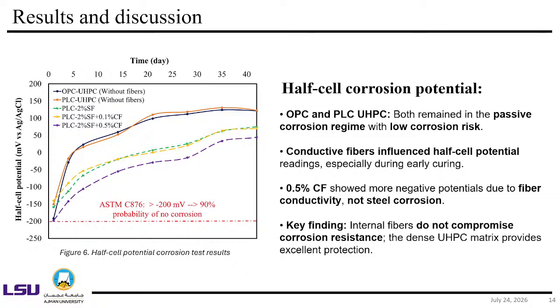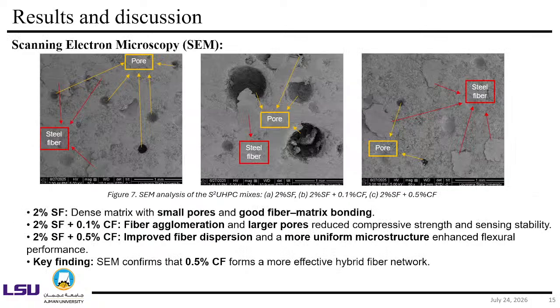And this line, for those who don't know, is the ASTM, the American standard for concrete. The standard says above this line there's no corrosion, so all performed quite well as an ultra-high performance concrete. Finally, we got some SEM images. Scanning electron microscopy just gives us a closer look at how the matrix actually looks. Here is 2% steel fiber without carbon fiber, 0.1% carbon fiber, and the most carbon fiber. We can see that this one has the most pores, the most porosity. This supports the previous theory for the lowest compressive strength.